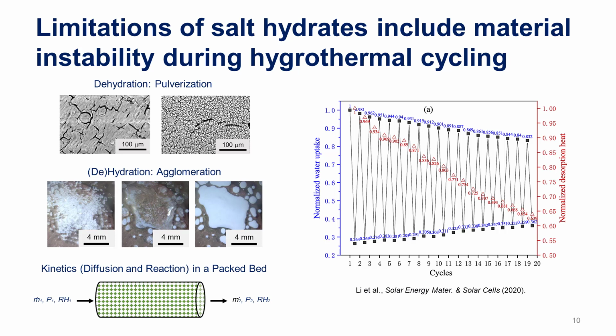So as a result of this, what you notice is in the first cycle, because again, this is a thermal battery, so we're going to keep charging and discharging it. So each charge discharge corresponds to one cycle. And so at the beginning, our energy density, so the red is the heat of the reaction or the energy density. You notice that just over 20 cycles, that energy density has dropped to 60% of the initial value. So very quickly, you start losing the storage capacity of the material because of these instabilities in the material. If it pulverizes or forms these agglomerated blocks, when we put it into a packed bed, when we're flowing water vapor at a given temperature and relative humidity, and you have these compact blocks, you're not going to have heat and mass transport through the bed. And so because of that, your energy density, like I showed you, can drop significantly.